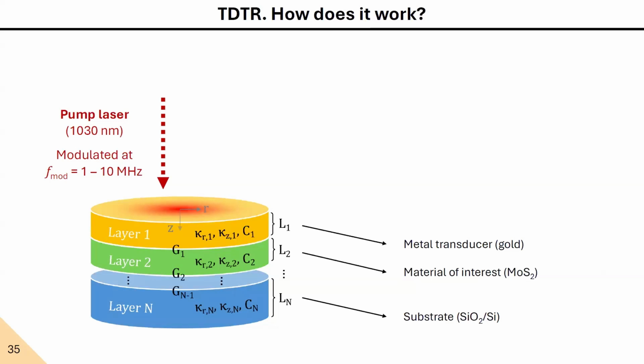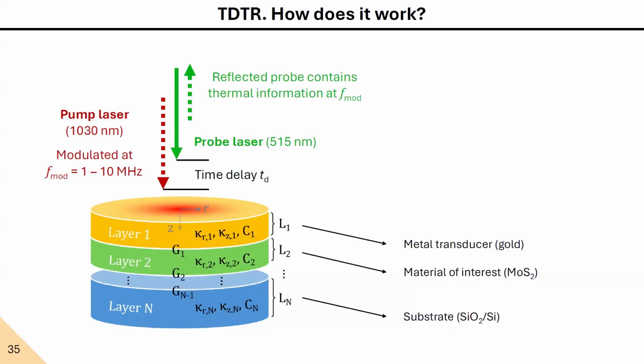So let's perform time-domain thermoreflectance measurements on our flakes. Our flakes are on a substrate and they have this metal transducer on top. We now use pulsed lasers and we modulate the excitation laser. This is the laser that introduces heat in the system. And we use a time-delayed probe laser, also pulsed, the reflectivity of which contains information at the modulation frequency of the pump beam. This is, we are detecting reflectivity changes that occur given the presence of the pump beam.